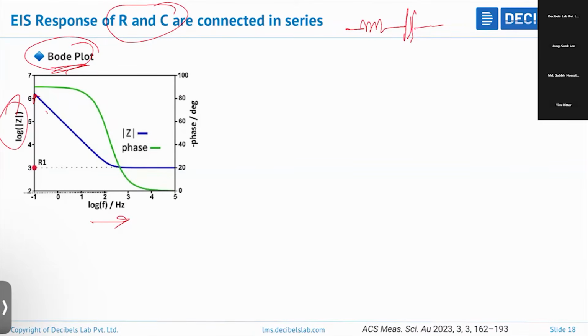You can see here the impedance decreases when the frequency is increased. At higher frequency it remains constant. This decrease is due to the capacitive behavior, and the impedance remains constant in this zone because it is independent of the frequency. This is because of the resistive behavior.